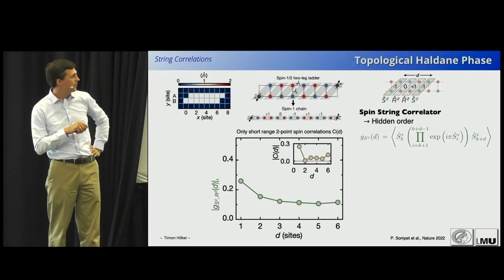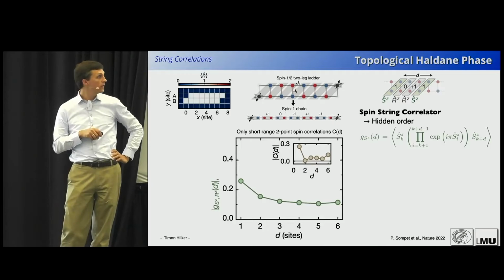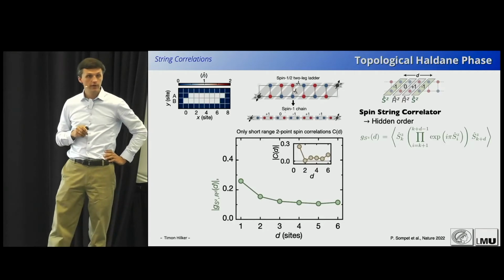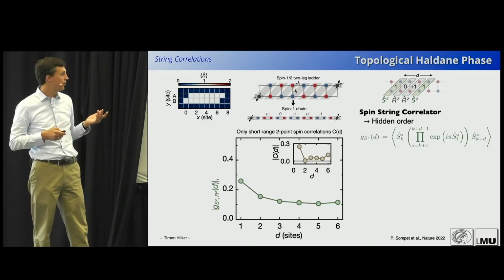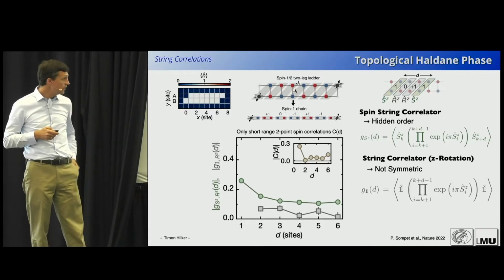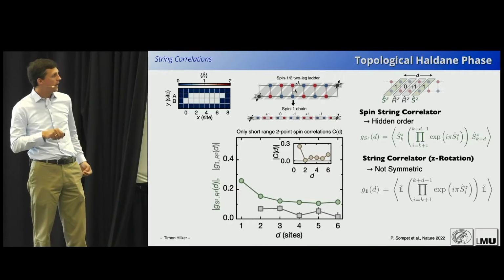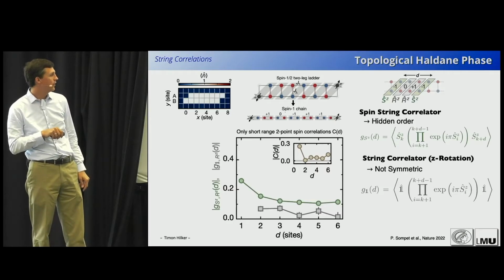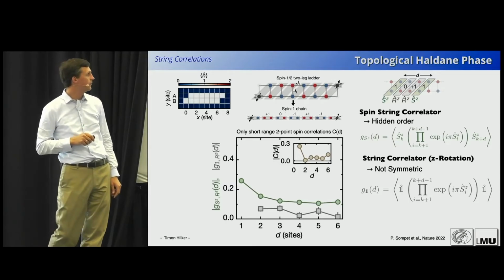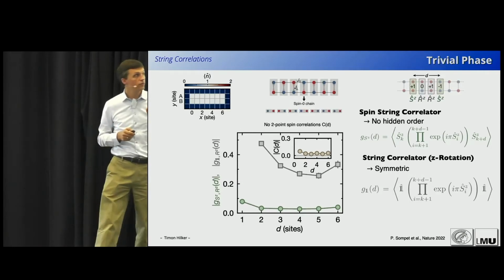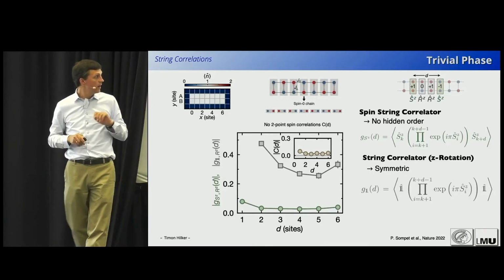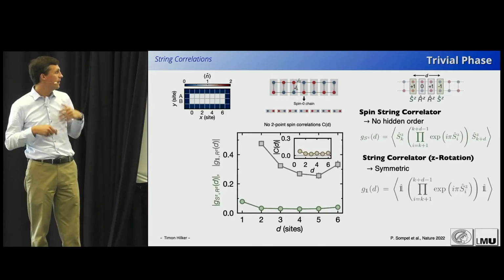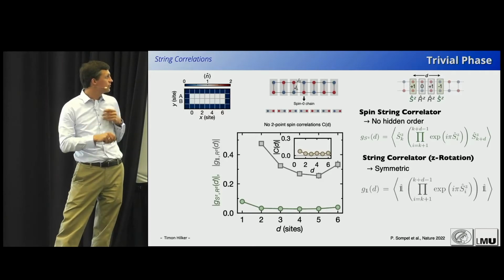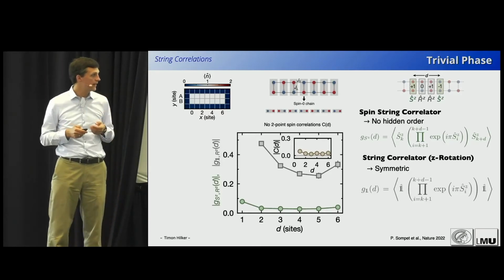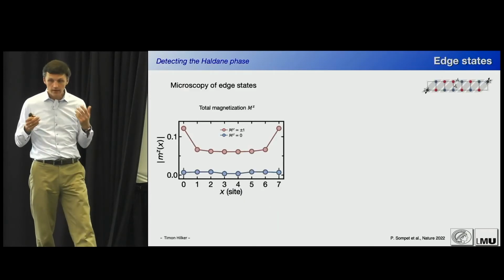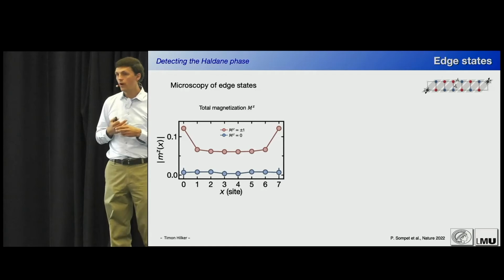One can then look at the normal spin correlations without this string, and yes, indeed, those decay to 0 really, really rapidly, consistent with this picture of local singlets. And then we can also analyze a second correlator, which is a string-only correlator, which should be 0 in this phase, and it does indeed become 0. If we do the same thing in this trivial phase I was introducing before, where we do the straight unit cells, we see exactly the reverse. So this all matches the theory that one expects at 0 temperature, just with different absolute values due to the finite temperatures. And the second main property of these systems is that they should show edge states.